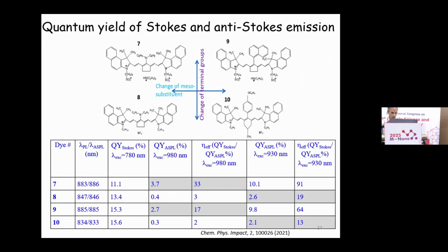Quantum yield of anti-Stokes emission is not high. Usually, it is small. So here you can see the numbers for the anti-Stokes emission. And also this anti-Stokes emission is dependent on the excitation energy, because as I showed you, dependent on the excitation energy, we extract electrons from different depths of the hot band, but population of this hot band is different, dependent on the energy level, which is realized due to the Boltzmann law, Boltzmann population law.